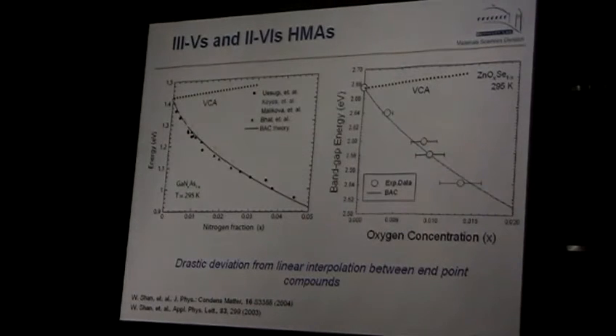And what happened was interesting, because if you have gallium arsenide, it has an energy gap of 1.4 electron volt. Gallium nitride has an energy gap of 3.4, so it should go up. But instead of going up, the band gap collapses. Basically, it starts to go down very dramatically. As you see, this is only 4 or 5% of nitrogen, and the band gap dropped by half an electron volt.